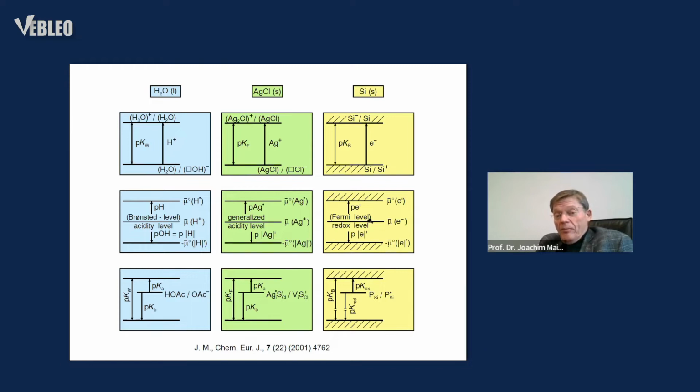The semiconductor people, they insert the electrochemical potential of the electron. It's not so important what it is at the moment if you're not interested in it, but it's a decisive quantity. Also, the Fermi level is another term for it, such that the distances to these levels are measures of electron and hole concentration. So if you take the same analogous quantity for the proton, then you can put it here in the middle again or somewhere in between, and then you have pH and pOH.